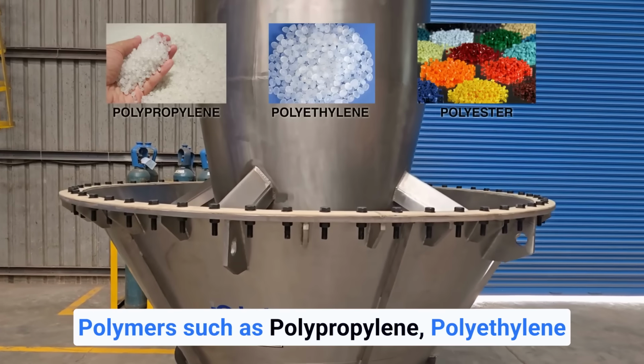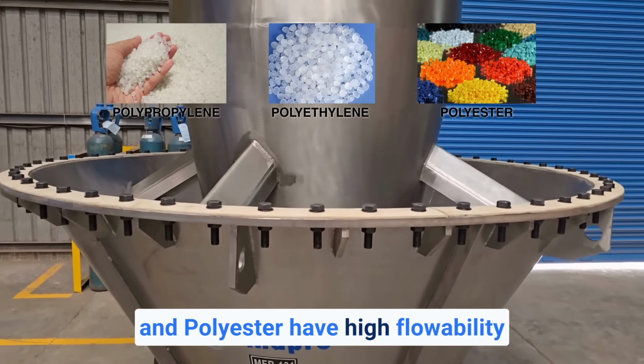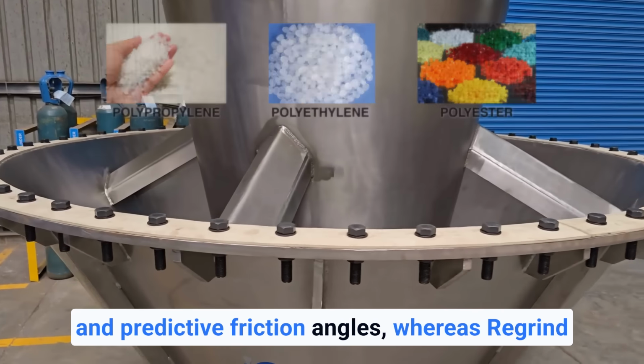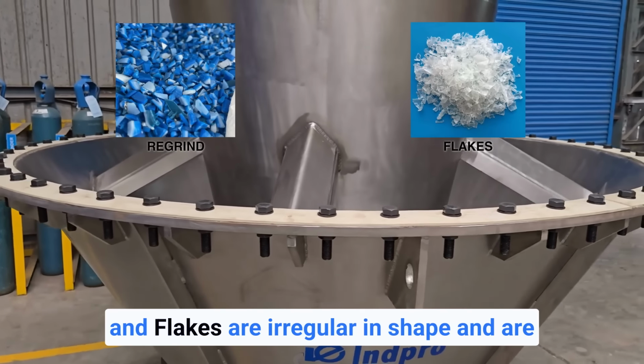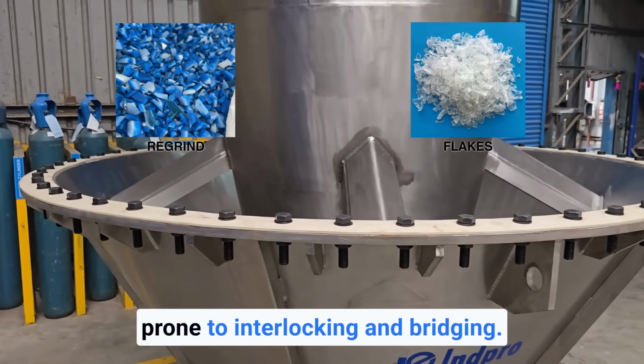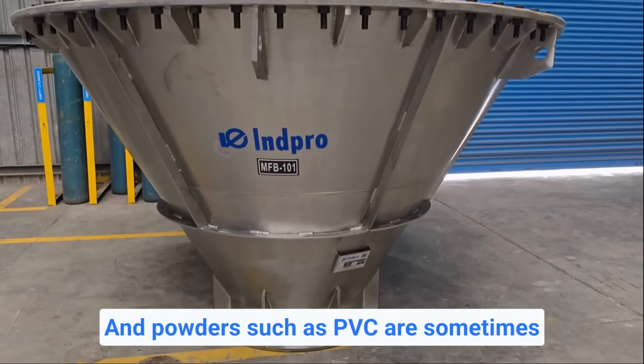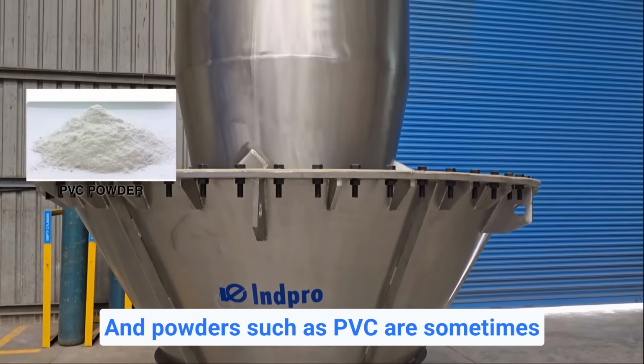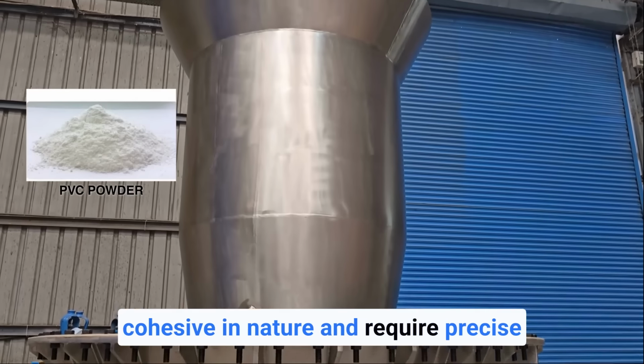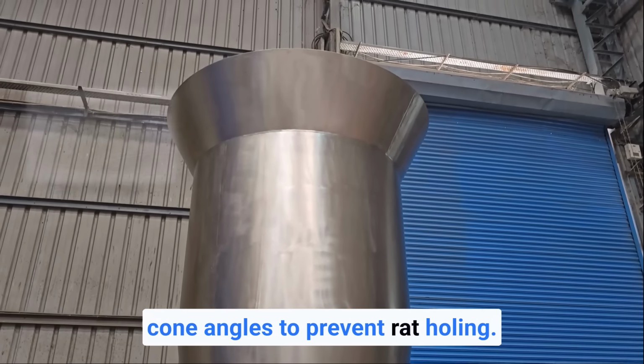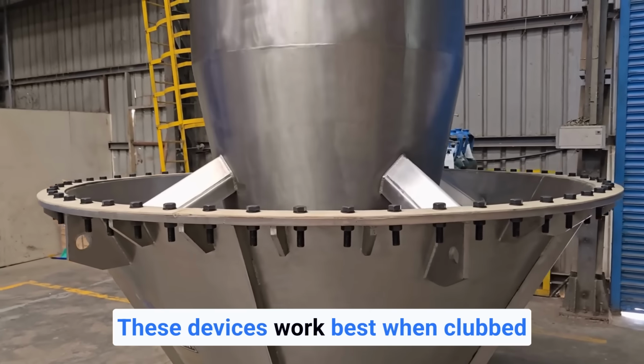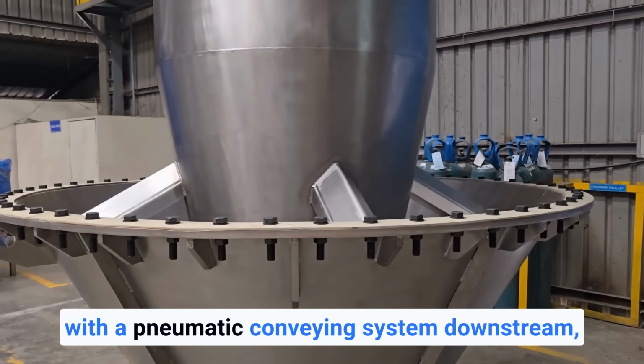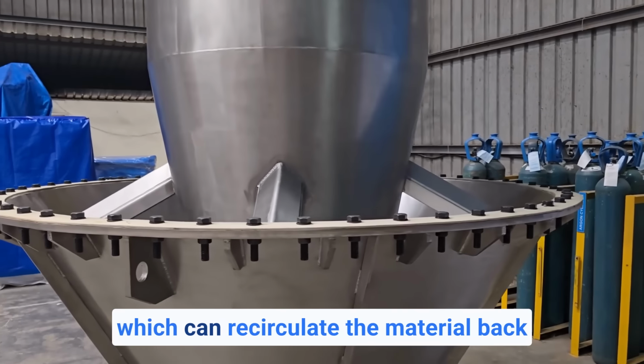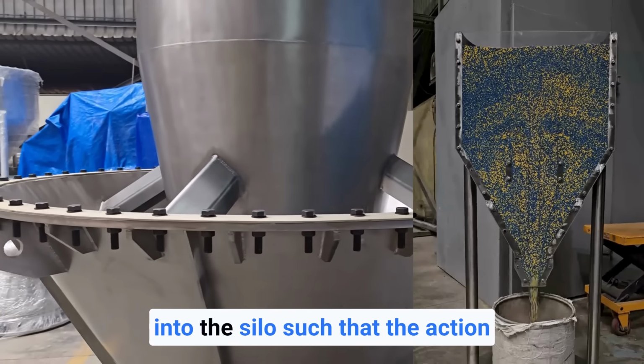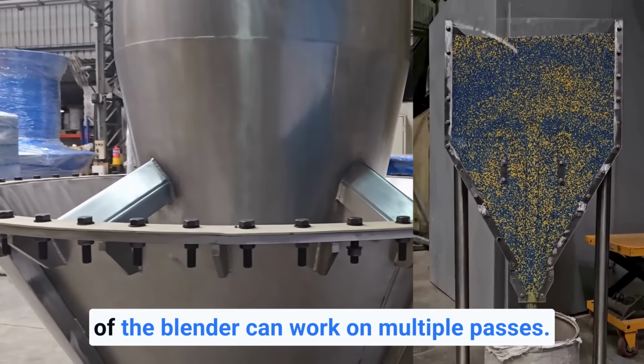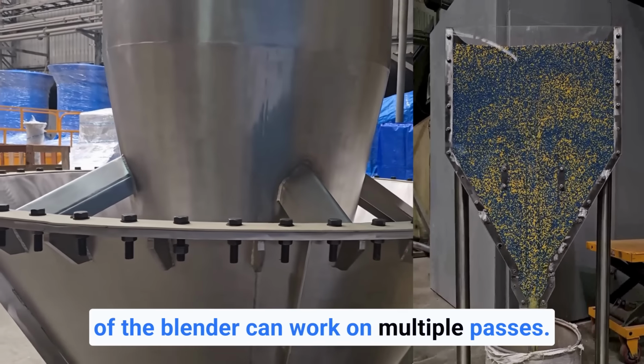Polymers such as polypropylene, polyethylene, and polyester have high flowability and predictive friction angles, whereas regrind and flakes are irregular in shape and are prone to interlocking and bridging, and powders such as PVC are sometimes cohesive in nature and require precise cone angles to prevent rat holing. These devices work best when clubbed with a pneumatic conveying system downstream, which can recirculate the material back into the silo such that the action of the blender can work on multiple passes.